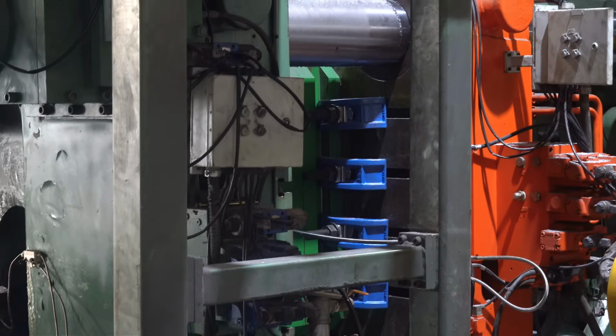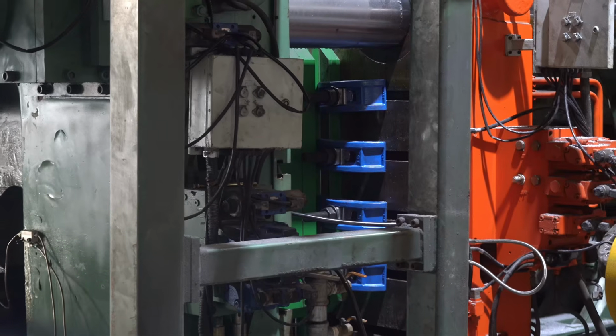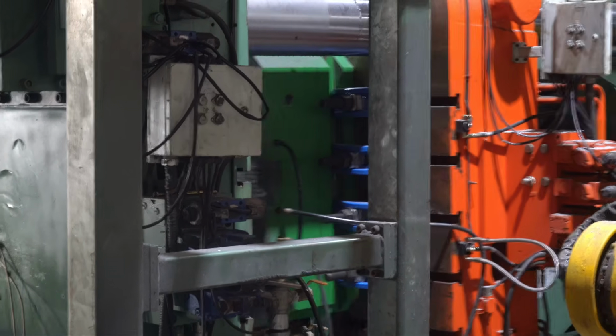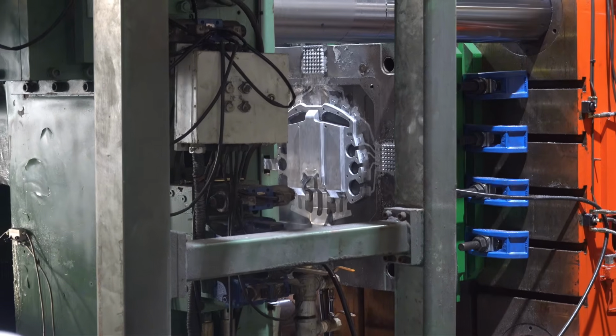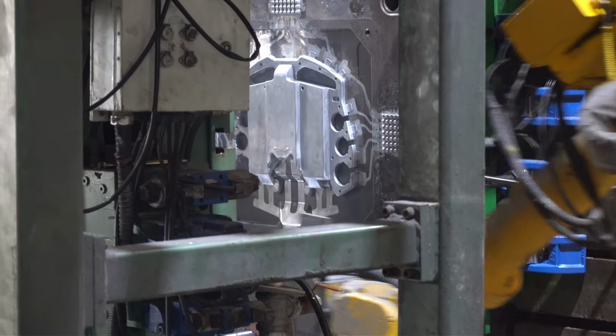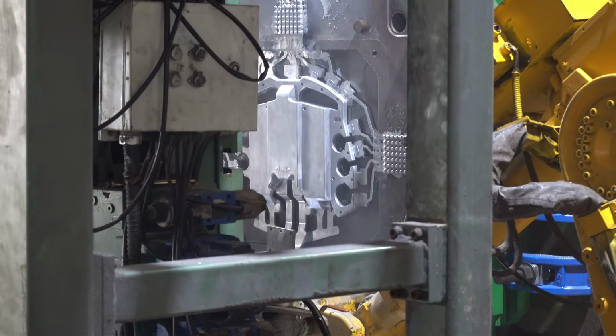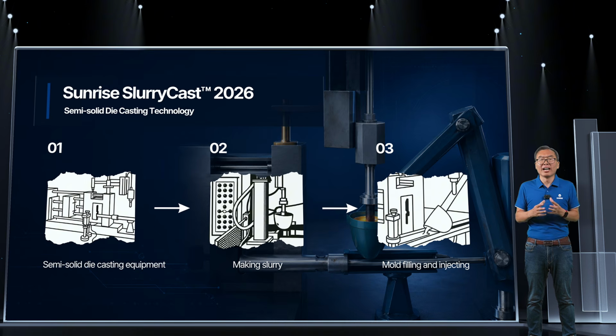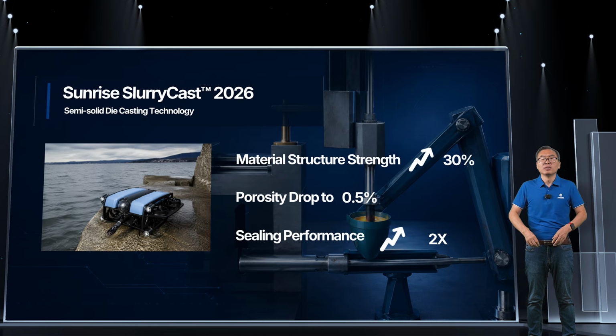We control slurry temperature, solidification, friction, stirring time, sealing time, holding time, transfer time, and slurry uniformity. In simple words, we are controlling the state of the metal before it enters the mold. With better slurry control, we can improve material structure strength by 30%, reduce porosity down to 0.5%, and support up to 2 times sealing performance in target applications.